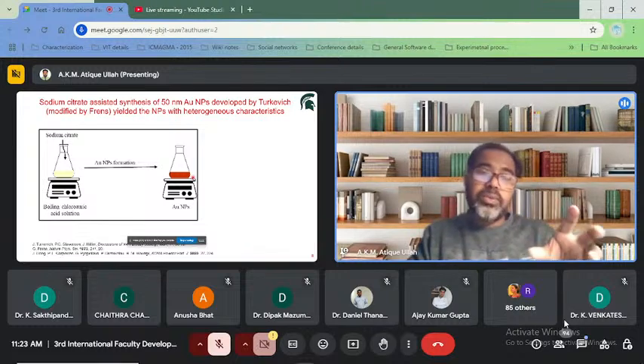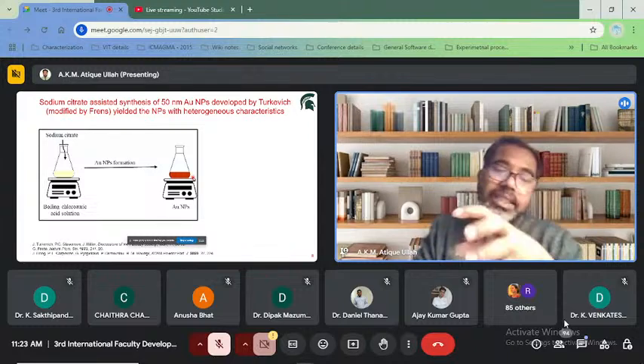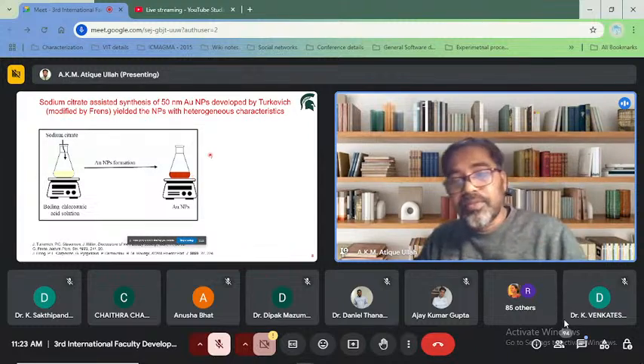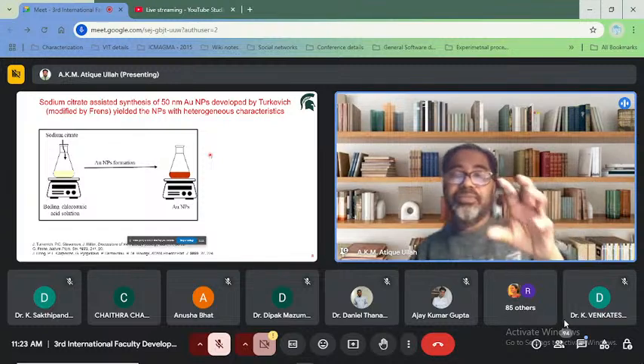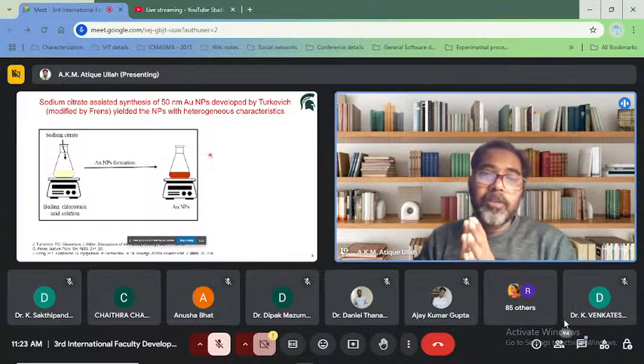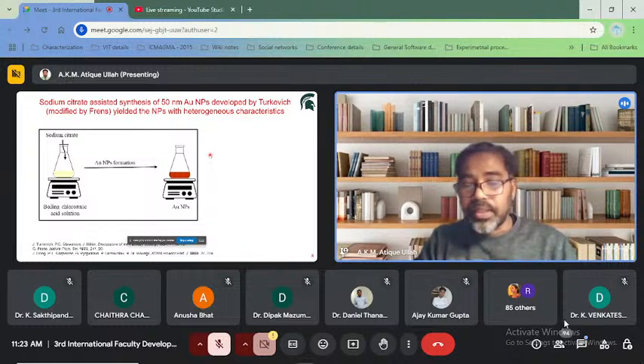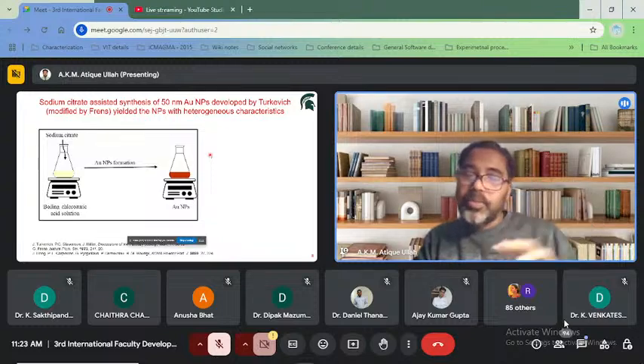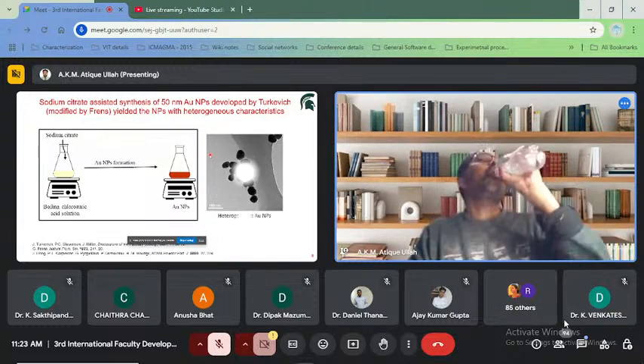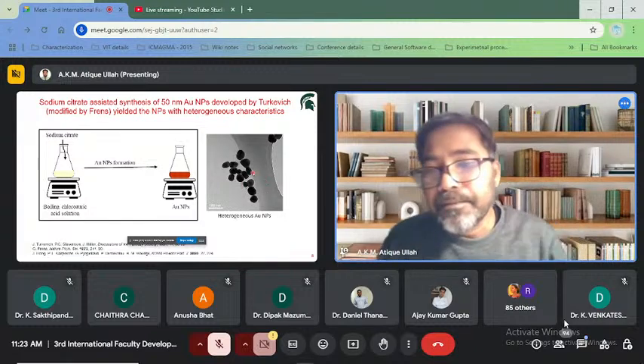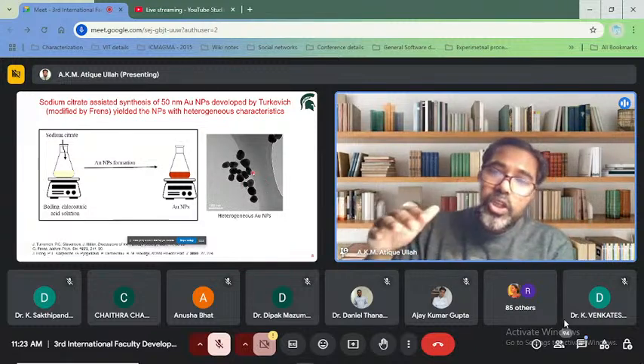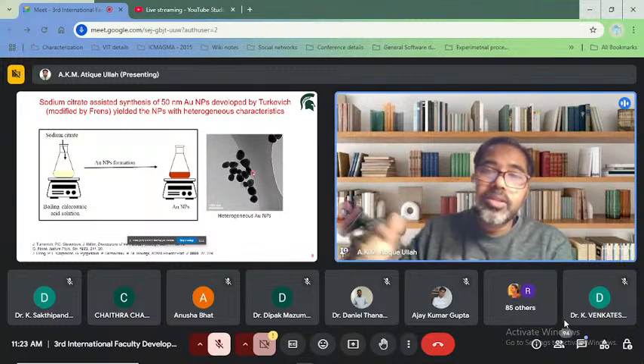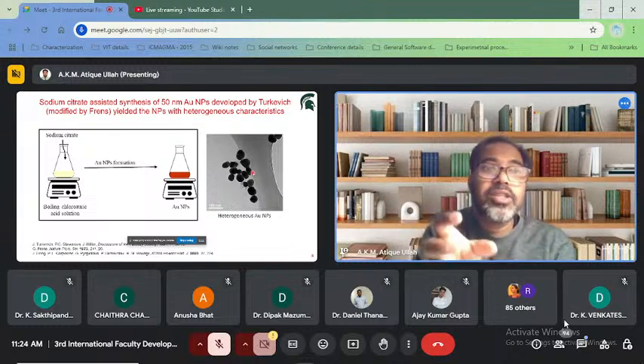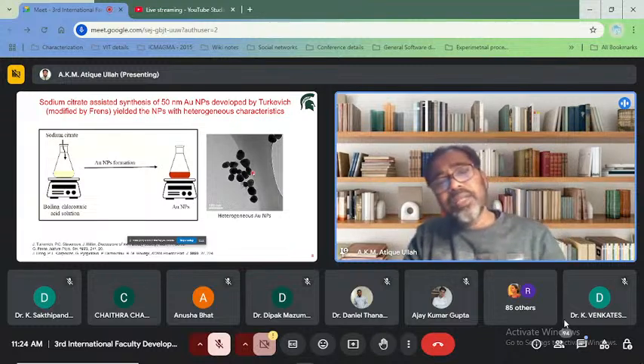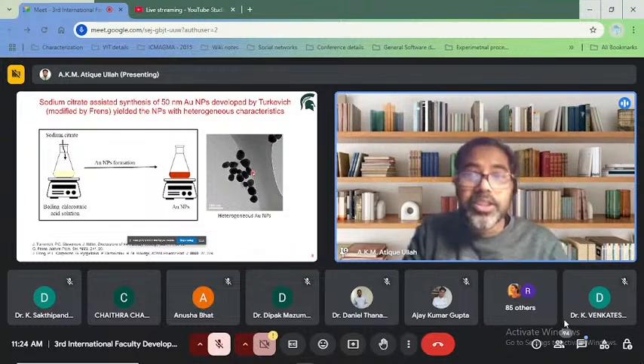But already I have mentioned that 50 to 60 nanometer gold nanoparticles show better performance as SERS nanoparticles. If we want to synthesize gold nanoparticles of 50 to 60 nanometer using this method, it is not possible to get nanoparticles with uniform size. You can see from the TEM image that usually we cannot synthesize nanoparticles larger than 30 nanometer using this sodium citrate assisted method. Then we searched for how we could synthesize uniform 50 to 60 nanometer gold nanoparticles.